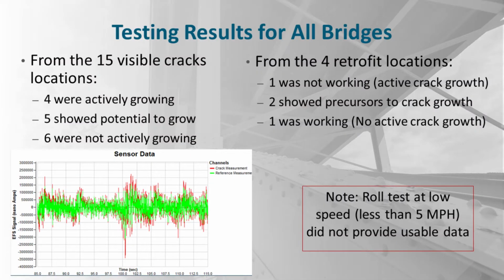But the results from the actual 19 total cracks, it was successful. From the 15 visible cracks, 4 locations were actually actively growing, 5 of them show potential to grow, and only 6 of them were not actually growing. With this information, you know how much damage you are actually putting into the structure, and what are the locations that are actually getting most of the damage due to the ambient traffic or the rolling test. And use this information to lower the rating of the bridge if necessary.